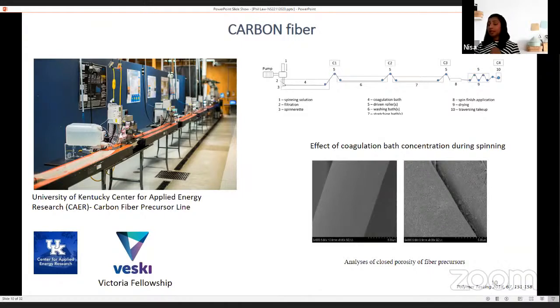We conducted various spinning studies by changing the coagulation conditions. In our study, we used 80% organic solvent. In another study, we changed the bath concentration to 77.5. We also developed a new method to measure the porosity of the fibers during the fiber spinning process. If you are interested, please check our article to learn more about this porosity measuring technique.